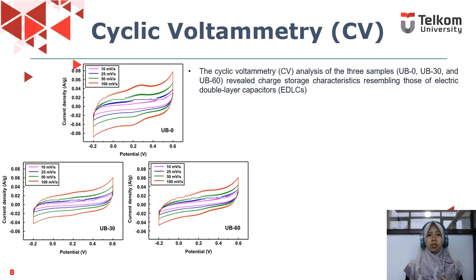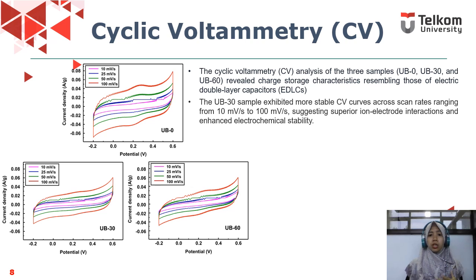The figure presents the CV curve of supercapacitor electrodes fabricated from three samples. The cyclic voltammetry analysis of the three samples revealed charge storage characteristics resembling those of an electric double layer capacitor. The UB30 sample exhibits a more stable CV curve across scan rates ranging from 10 until 100 millivolt per second, suggesting superior ion-electrode interaction and enhanced electrochemical stability.